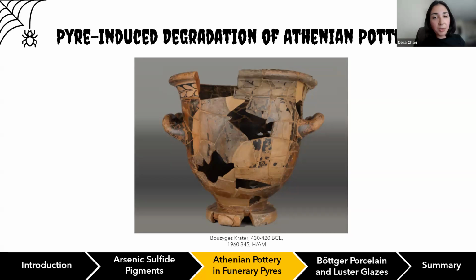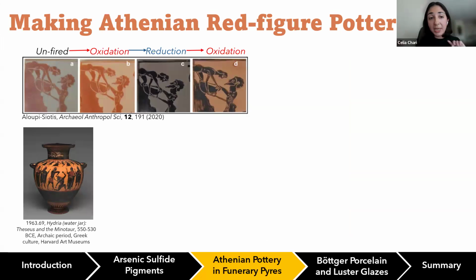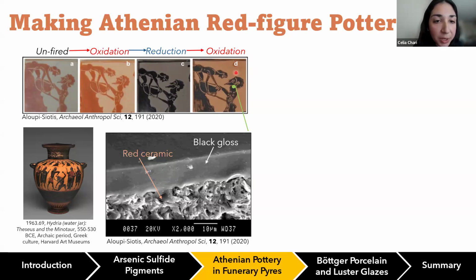But before I do that, I wanted to first introduce to the audience how red figure is made, because I think all ceramists will appreciate this really complicated firing process that goes through a series of oxidation, reduction, and oxidation steps. So ultimately, what you're left with in red figure pottery is this layer of black gloss that is over a porous red ceramic. The red that you see in the final crater is just the ceramic substrate, and all of the black highlights are made of this black gloss. So how is this made?